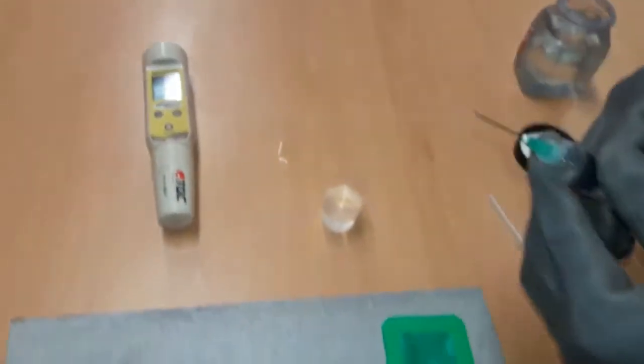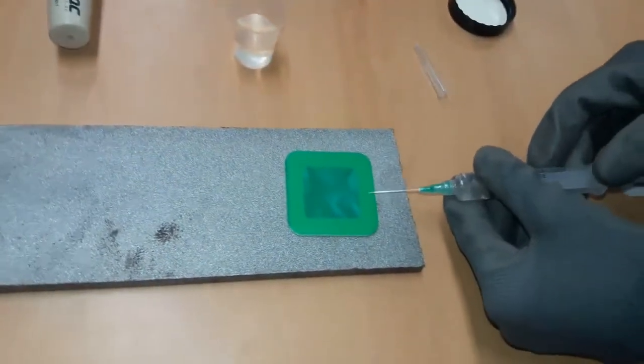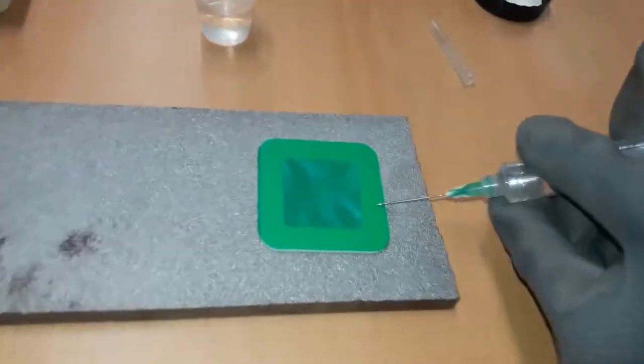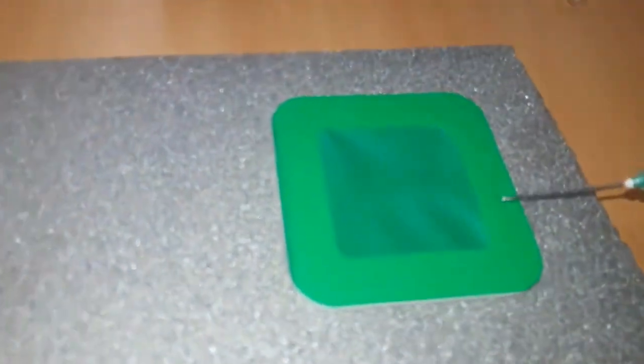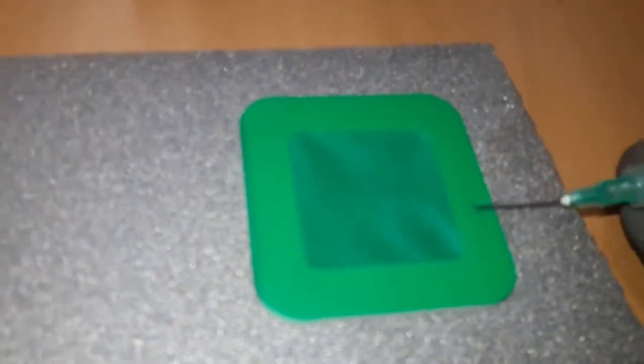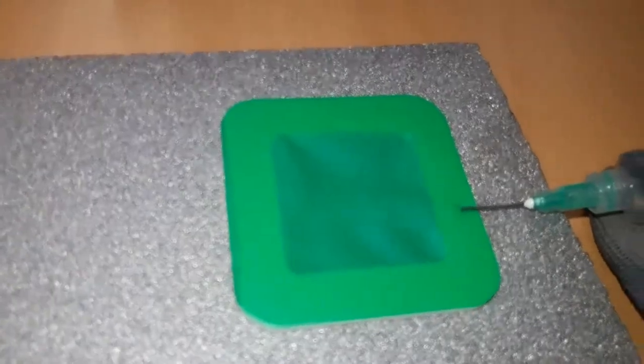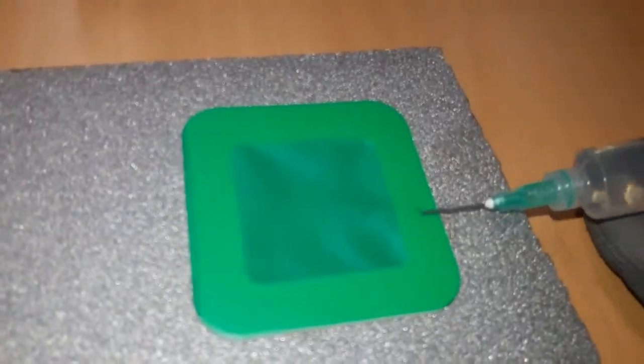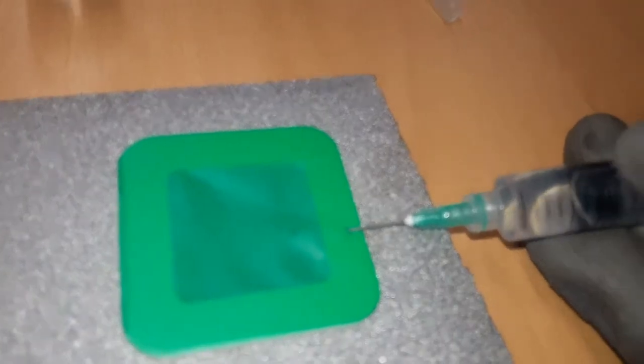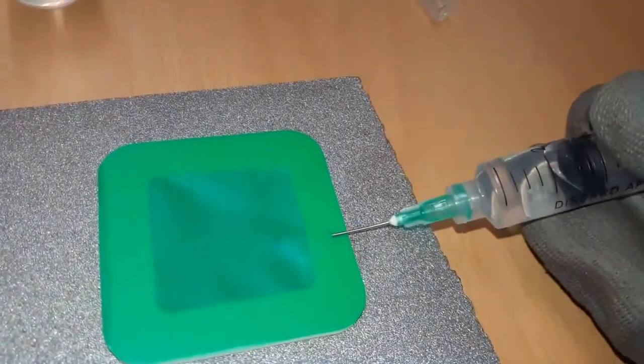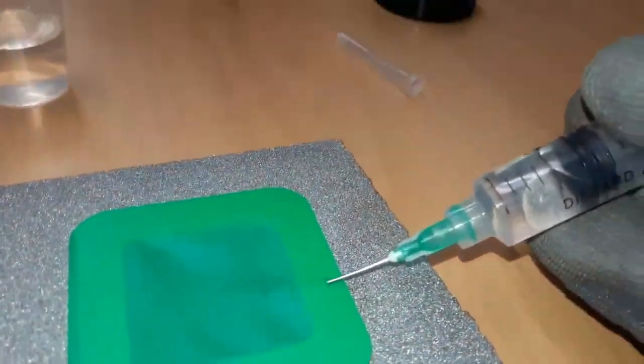Insert the syringe needle at an angle of 30 degrees to the test surface near the outer edge of the patch, so that it passes through the adhesive foam body of the patch into the compartment formed between the elastomer film and the test surface. If the patch is in a position which makes access to the patch compartment difficult, bend the syringe needle as required.